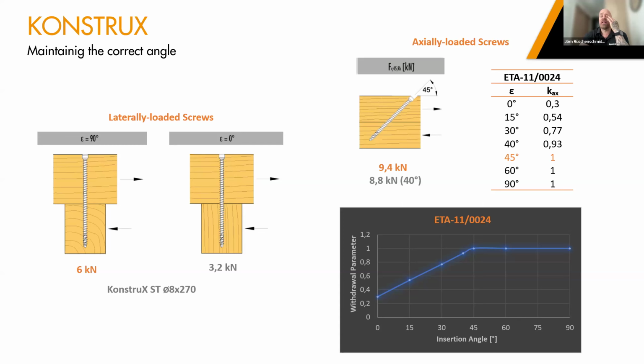But especially when we look at the angled installation of screws, where we always aim for the 45 degrees, I guess many people are not aware how a change in angle will change the effectiveness of the screw if we differ from the intended axial load direction. Being at 44 or 43 will not be of a big change. But as you see, as soon as we come to 40 degrees, for example, we reduce by approximately 7%. And the more we go into the shear plane, we reduce even up to only 30% of the initial capacity of the screw.